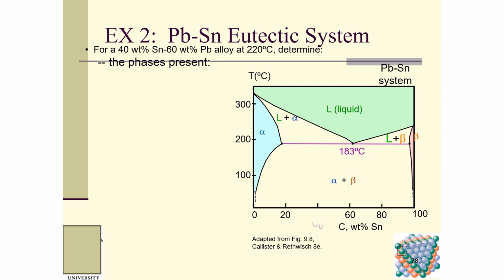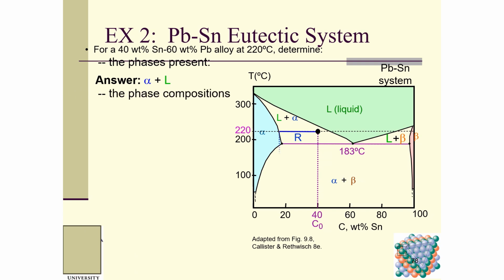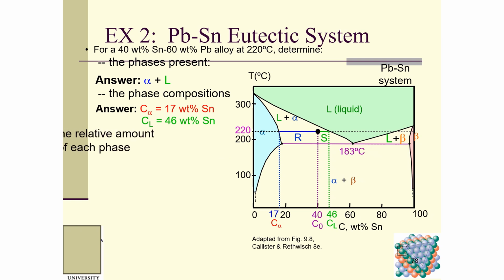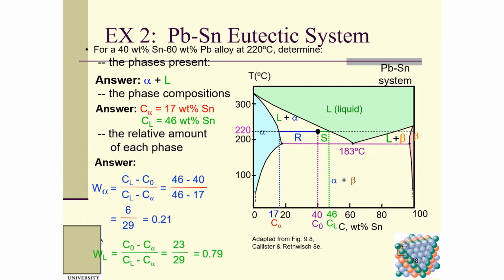Example B, the phases present for 40 weight percent Sn at 220 degrees C. Here, this is alpha plus L. The phase composition, and draw a line. Okay, draw a line here. So from here to here. So C alpha is 17% and C liquid is 46%. The relative amount of each, the weight fraction, we use the lever rule to calculate and draw a line. Okay, S R. Be careful, S R.